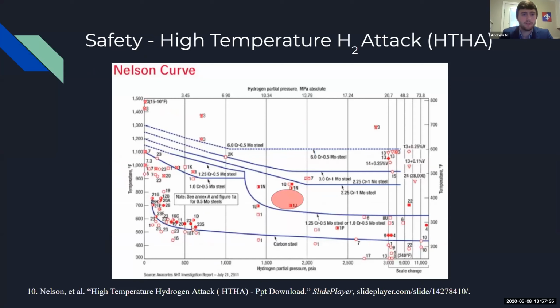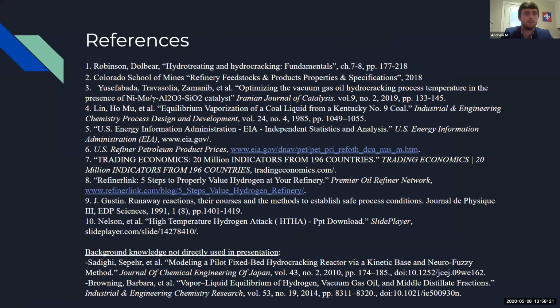The last safety aspect we looked at was the phenomenon high temperature hydrogen attack, which happens with hydrogen at certain high temperatures and pressures inside a vessel made of high carbon content. The hydrogen can actually diffuse into the vessel's walls and react with the carbon, creating methane gas, which can cause small cracks inside the vessel. And then over time, these cracks can get larger and possibly cause a catastrophic failure. And as you can see on this Nelson curve shown here, it is much higher than the metallurgical limits of carbon steel. So what we decided to use for our reactors' metallurgy was chrome steel with a stainless steel welded overlay. And those are our references.